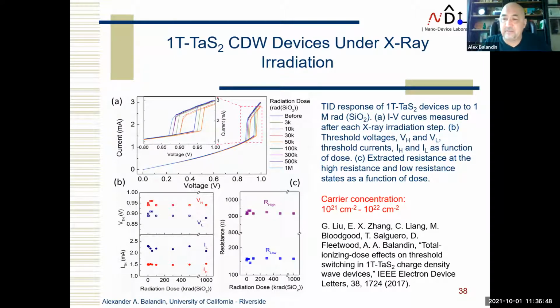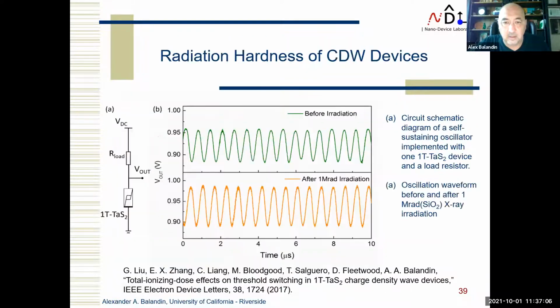As a result, if you have a trap that takes an electron away from the channel, nothing happens because the carrier concentration is very high, and it's also a 2D geometry, and we don't care about the Dirac point or anything like that, because this is an essentially two-terminal device driven by a series resistor. Okay, and as you can see here, we sent the device to Vanderbilt.